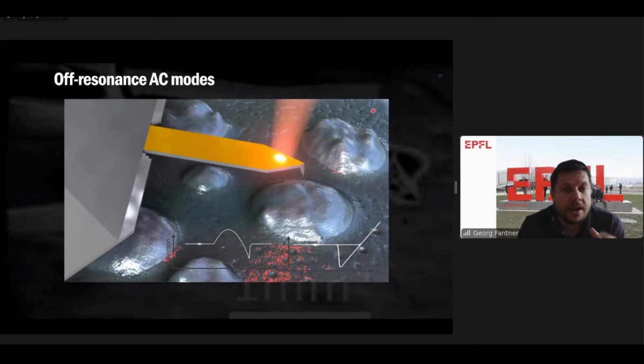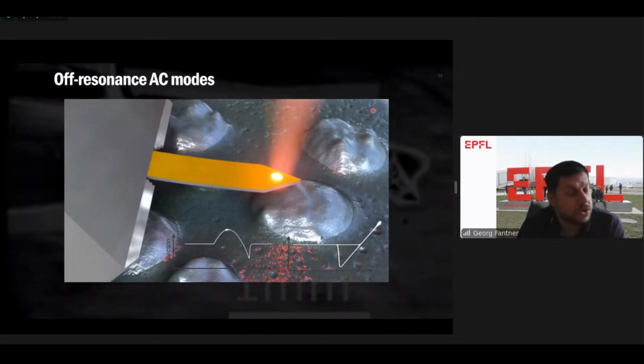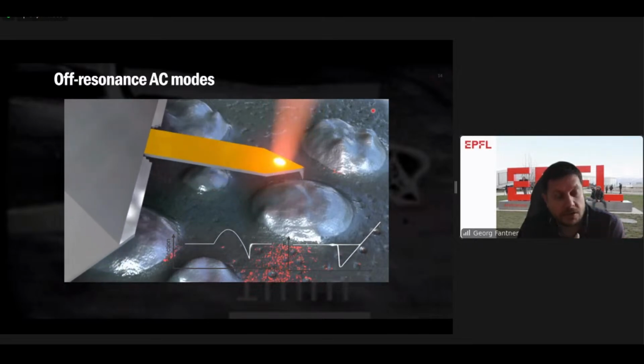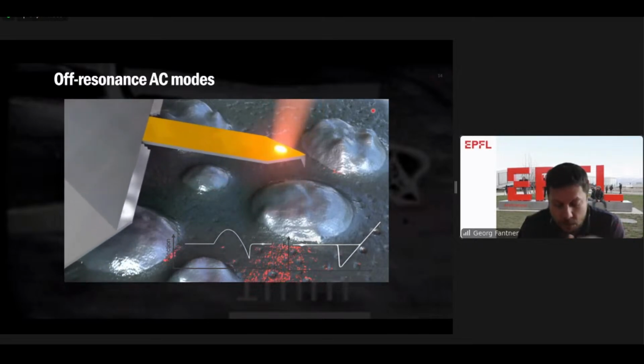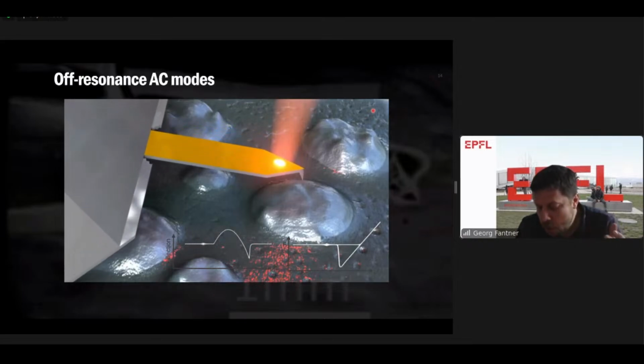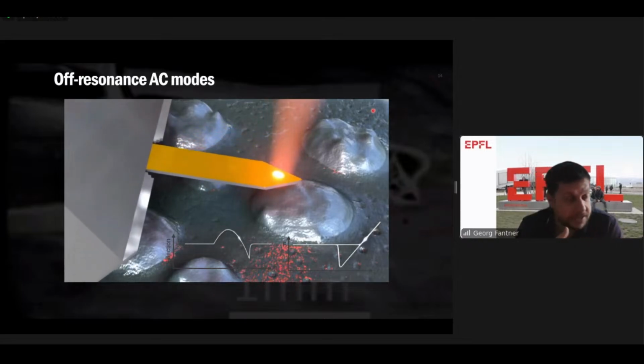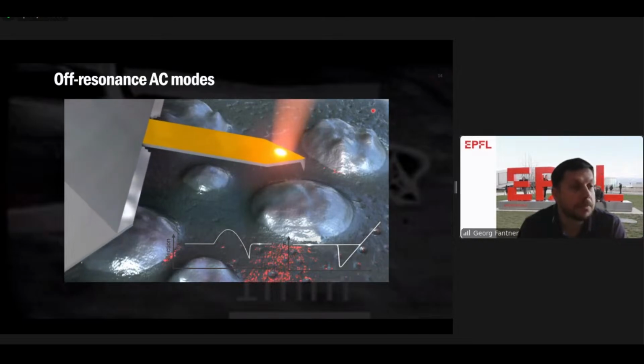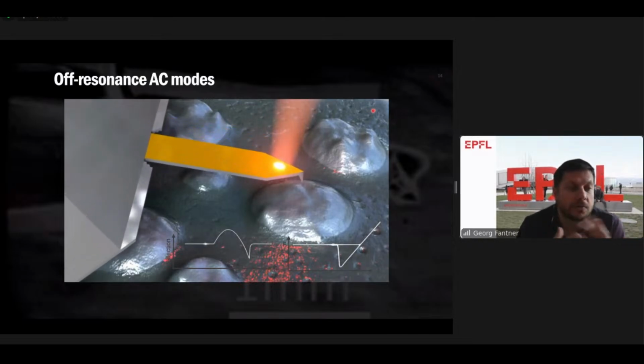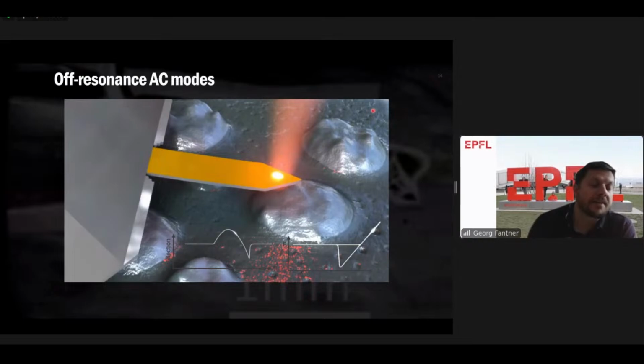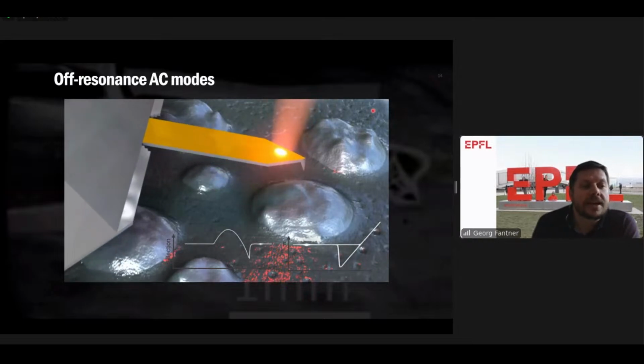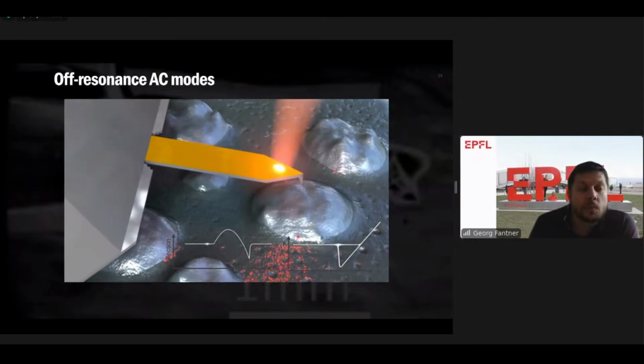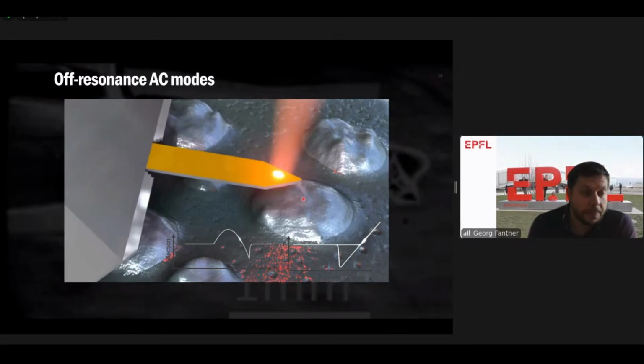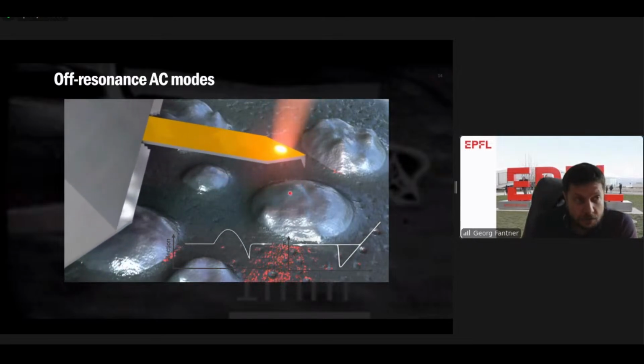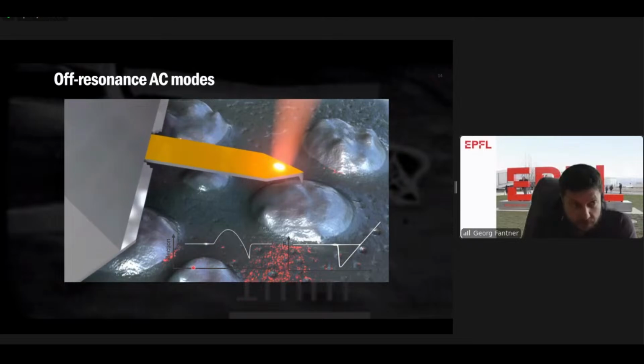And there's actually a number of different commercial implementations of this off-resonance mode. You may know it as peak force tapping, or you may know it as QI mode or hybrid mode. All of those work in a similar way. And they have the very big advantage that you are getting one interaction curve per pixel, irrespective of the Q factor of the cantilever, at least to first order.